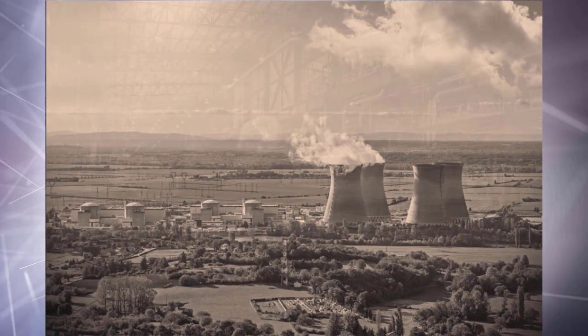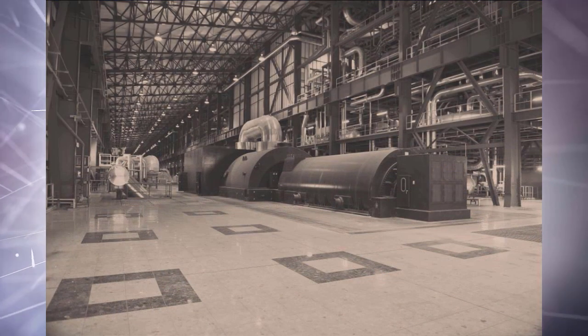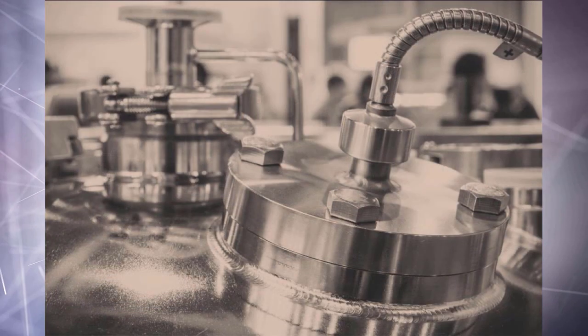Surface analysis was really impossible when I became interested in it. It goes right back to my PhD which started in 1958, looking at the growth of films which became stable at about 200 nanometers on Magnox alloys. Magnox alloys were used to clad uranium in the first generation of commercial nuclear reactors. My job was to understand the best alloy composition. It was frustrating — we could measure the thickness and follow its behavior over months but we couldn't tell what it was made of.